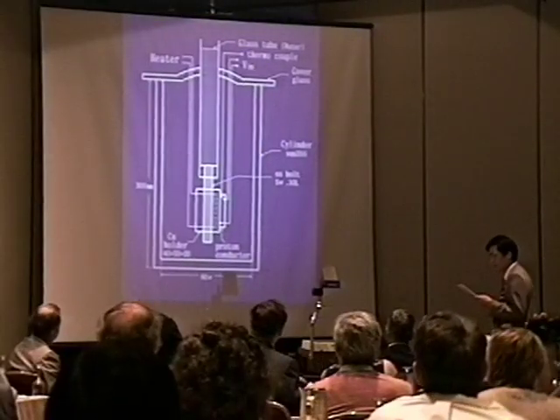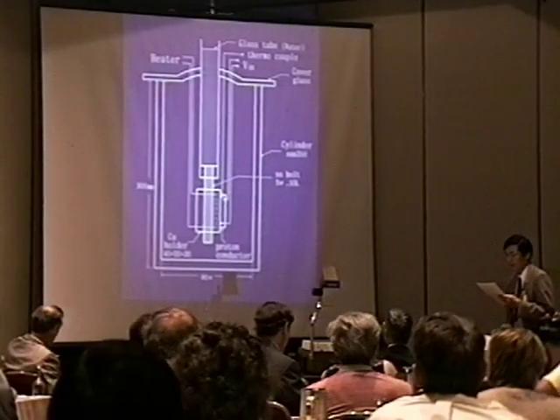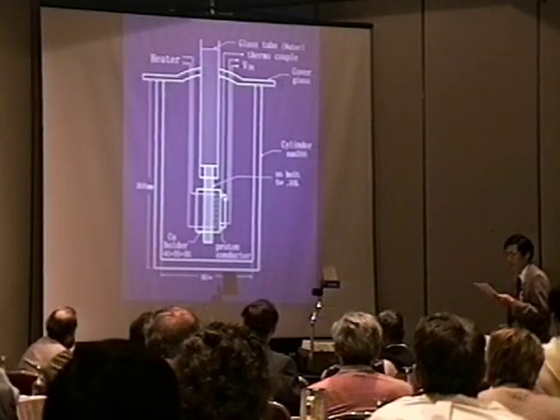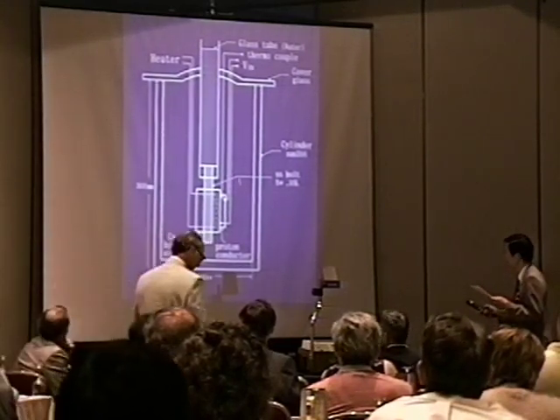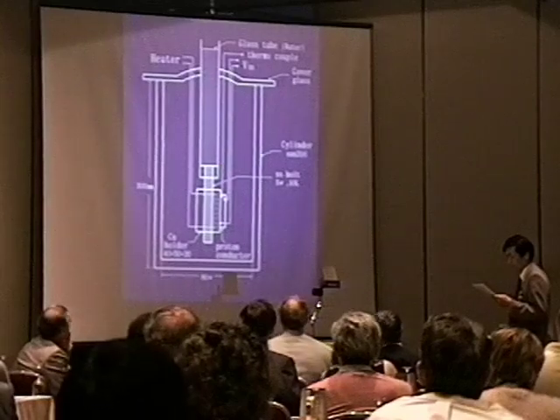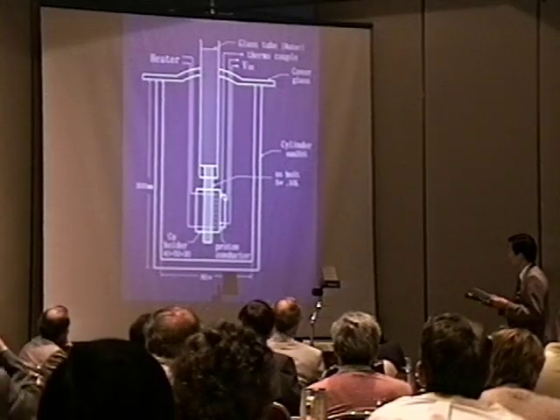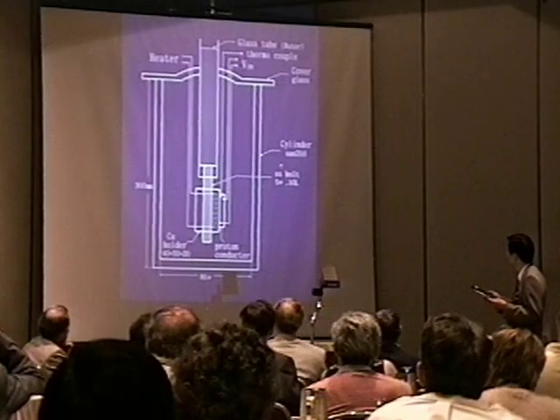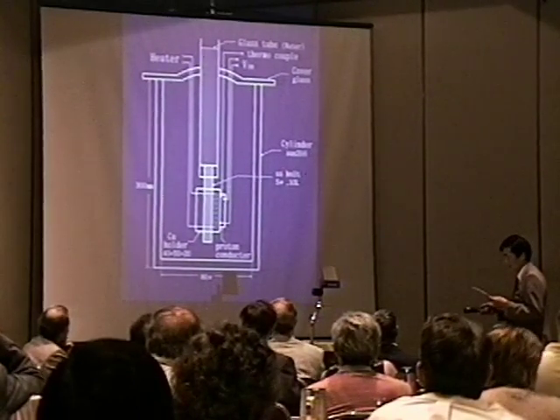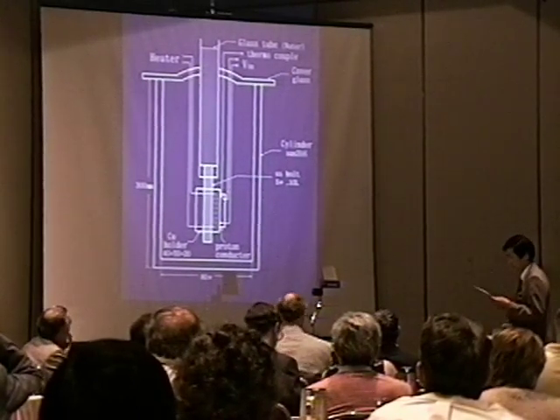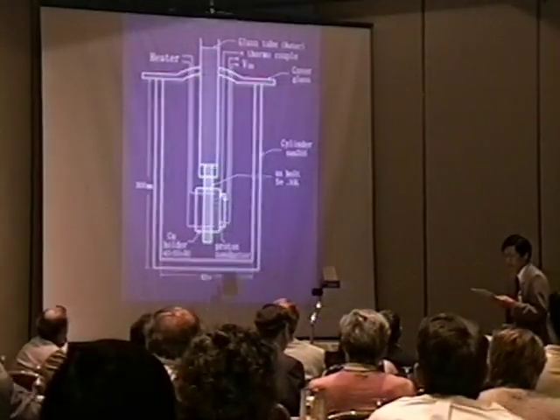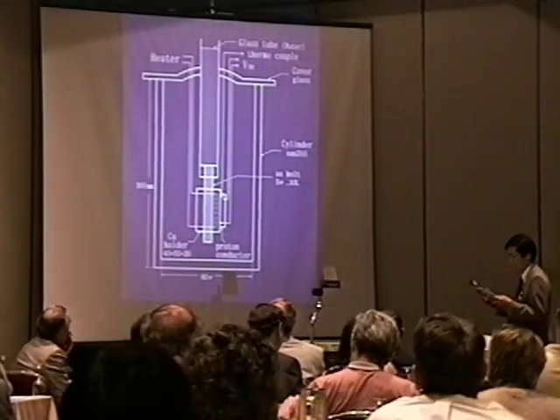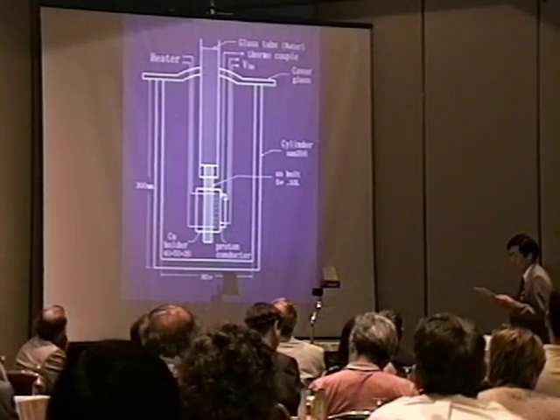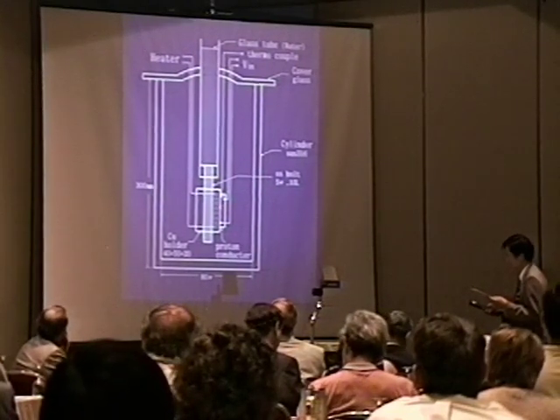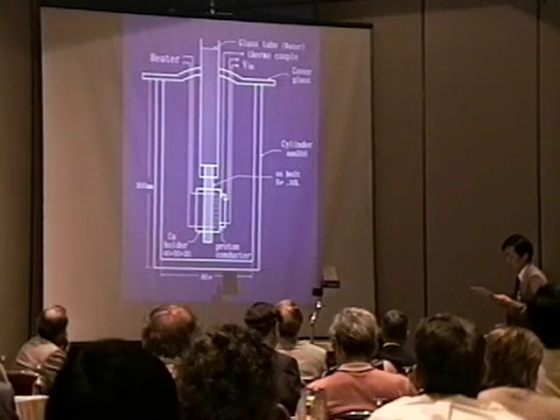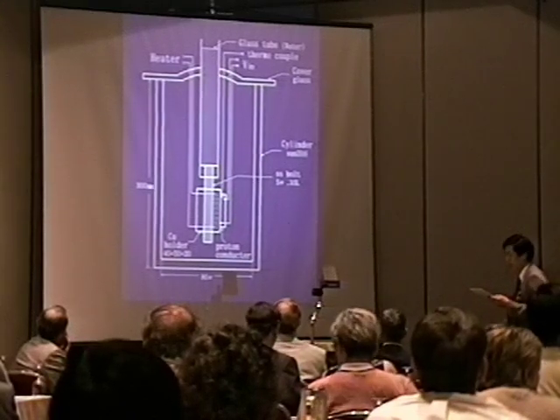This is a schematic drawing of the reactor system. The reaction cell is made of a 5 mm thick stainless steel cylinder with 8 cm diameter and 30 cm length. The upper part of the cell is covered with a glass cap. A sample was held with platinum plate of 1 mm thickness. Pressed from both sides, they are fixed to a copper holder.